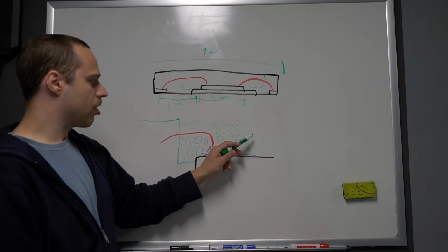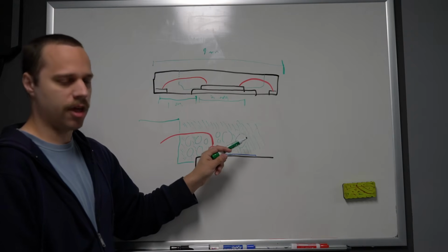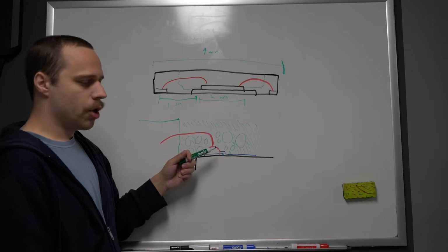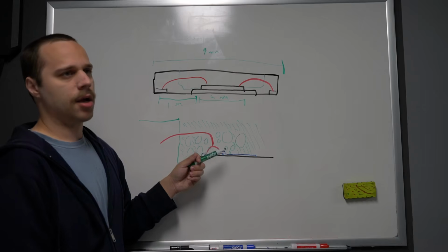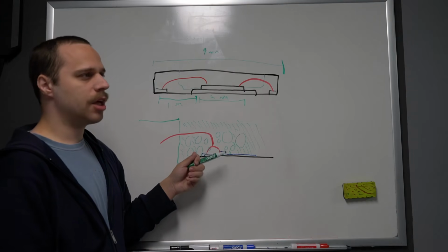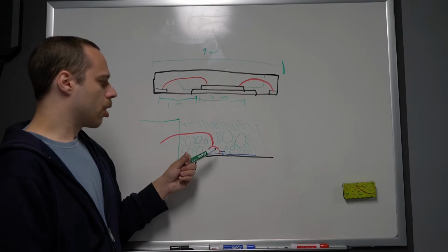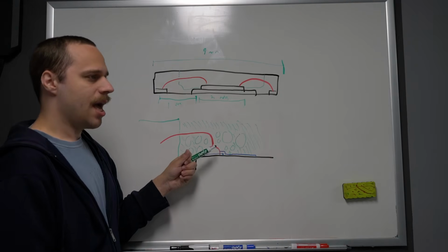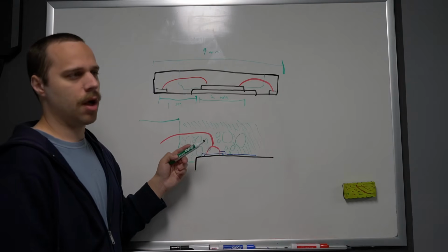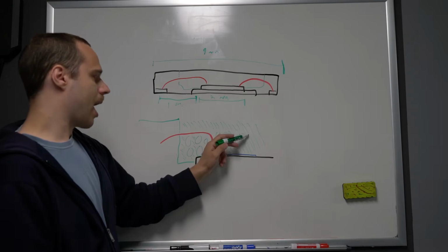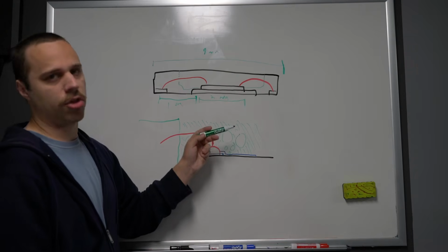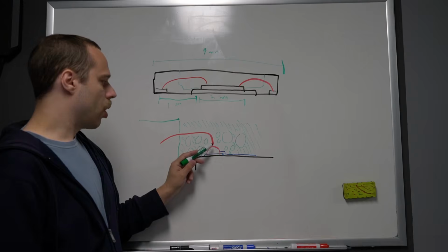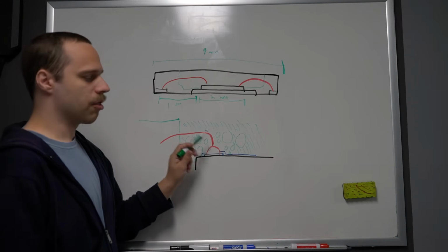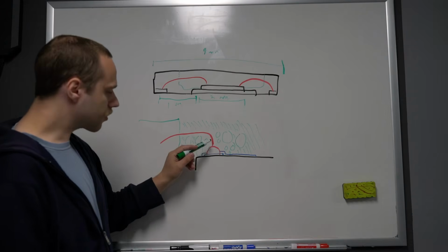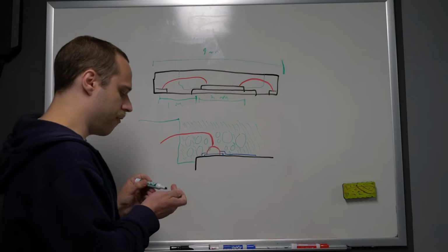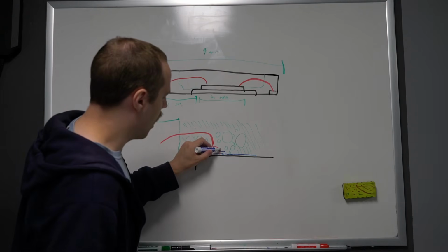Now, the sulfuric will oxidize the organics if you get it much, much hotter, like 200-300 C, but we're not going to be working anywhere near that hot. When the sulfuric is present at lower temperatures, it will dilute the nitric, but do so in an anhydrous environment that still keeps the pH very low, and the sulfuric will try to grab onto the remaining water in the nitric and give us essentially a reaction environment that is free of available water. So we get the nitric reacting with the organics. The silicates essentially just sit there and are flushed away during the cleaning stage, and the sulfuric is going to hold on to both the water generated by the breakdown of the epoxy as well as the water present in the 70% nitric. And so ideally what we get is this film of passivation material on the surface of the metal.